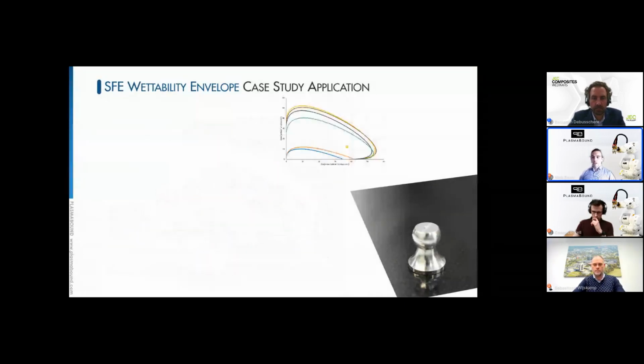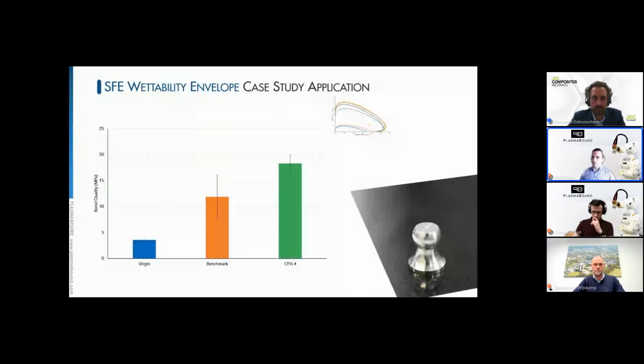What we saw statistically was a significantly higher bond strength with the samples that were prepared under CPA4 compared to the benchmark material, but also the sporadic nature of the failure was considerably reduced. So the statistical significance was that the customer could put this in service, be more confident that there would be a stronger bond for a longer period of time, and that more of the products would have that bond than in the case of the benchmark, where some of the products may have a variability in their bond.